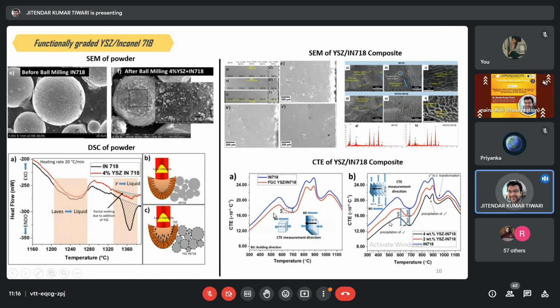So here basically, I must say that this particular sample is experiencing lower thermal expansion when we compare it with the Inconel 718, because the yttria stabilized zirconia has a lower thermal expansion value. So what is happening? It is affecting the coefficient of thermal expansion of the parent material. Around 6% decrement is observed when we are observing perpendicular to the composition gradation.